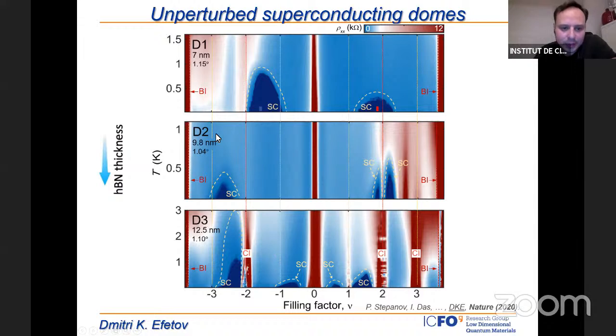If we go up to device 2 and device 1, what happened here is we slightly detuned the twist angle to smaller and larger values. So we increased theta, and also we went to thinner hBN. Here hBN is now 7 nanometers. What we find, and this is visible in the top phase diagram, is that we don't see those correlated insulators anymore. For example, here we would expect a correlated insulator, and at -2 here we would also expect one. These are gone, but strikingly, the superconductors are not gone. The superconductors are still there in the data.